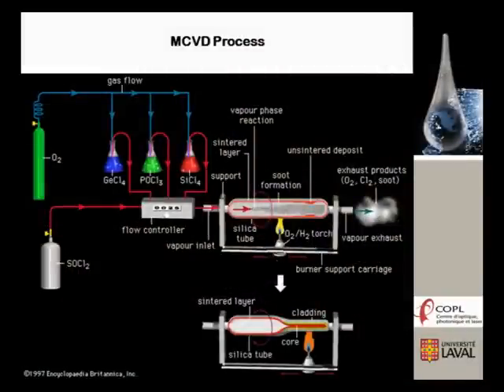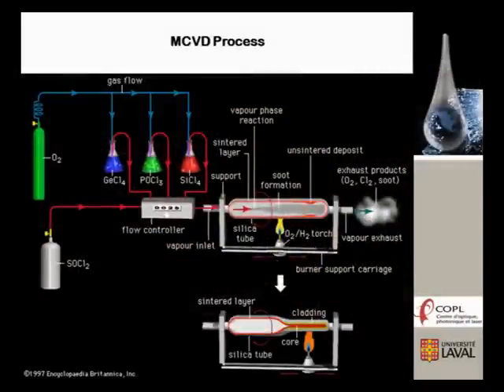Now, we start with this chemical deposition, then we want to change the refractive index, we put in germanium, or again, we want to lower a little bit the refractive index, we go with phosphorus, and this is coming through a controlled-flow system, and coming inside our silica tube. Normally we buy this tube from the Heraeus company, a higher quality, it's very expensive of course, with a high purity of pure silica glass, SiO2, and we make deposition inside this material, and you can see here these particles we have in the vapor phase, and here we control what we call the oxidation process.